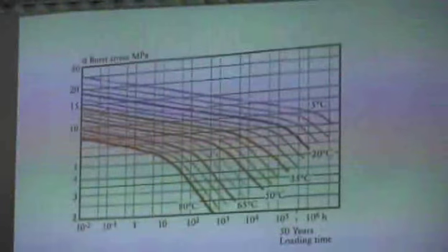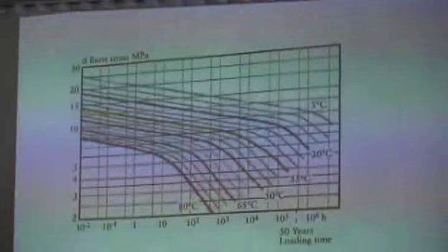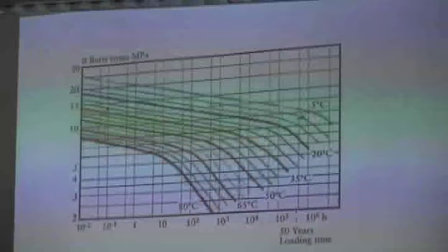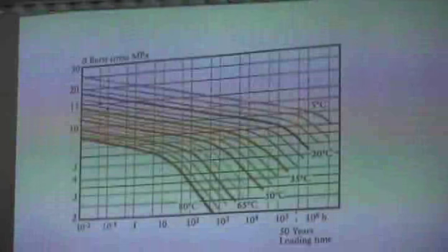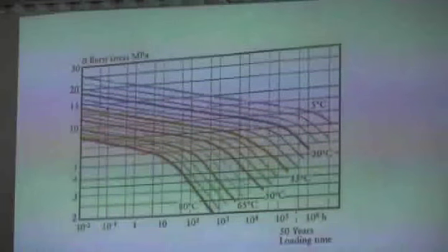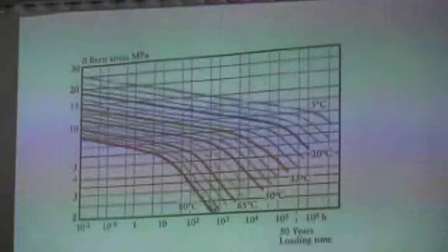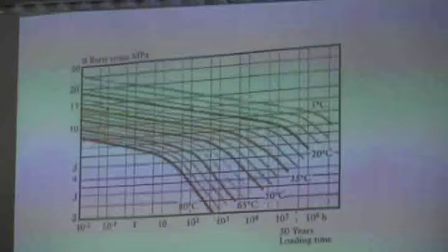And I can only do it if I know if I have a transition, or where the transition is going to be in behavior. You can see from this plot that the transition point with respect to temperature is very steady. So what it tells us is, I can run my test at higher temperature because it doesn't take as much time. I'll go through that transition over here. It may take me 1,000 hours. In 1,000 hours, I get the whole red curve at 80 degrees.